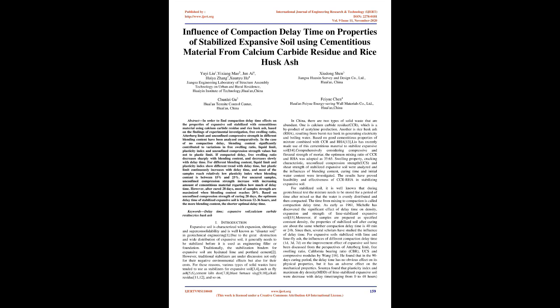with delay time, and most of the samples reach relatively low plasticity index when blending content is between 15% and 25%. For uncured samples, unconfined compression strength increases with increasing amount of cementitious material regardless of delay time. However, after curing 28 days, most of the samples' strength is maximized when blending content reaches 20%.